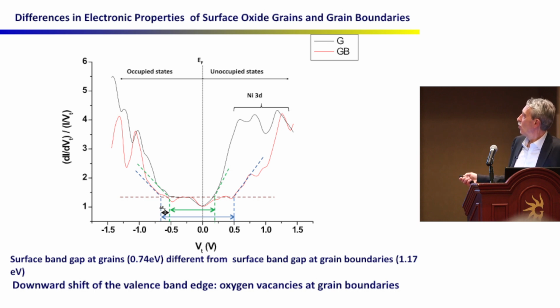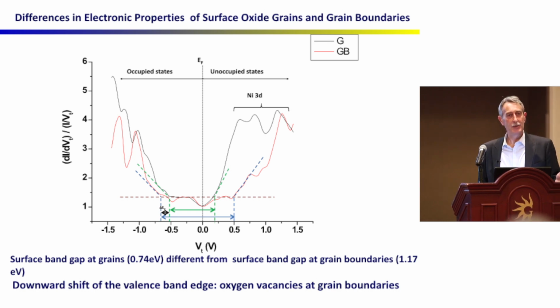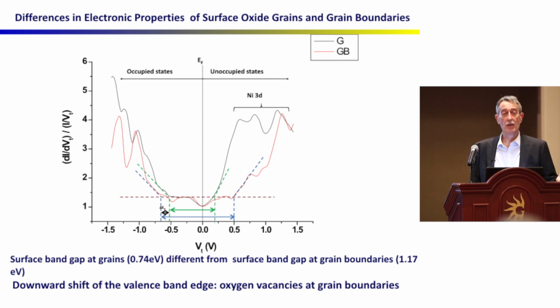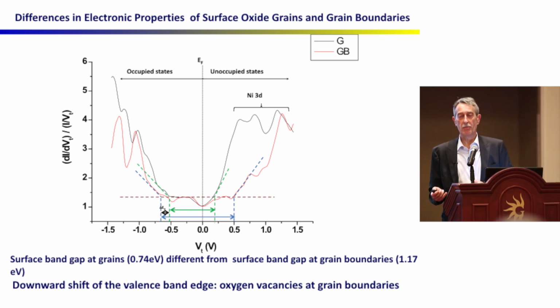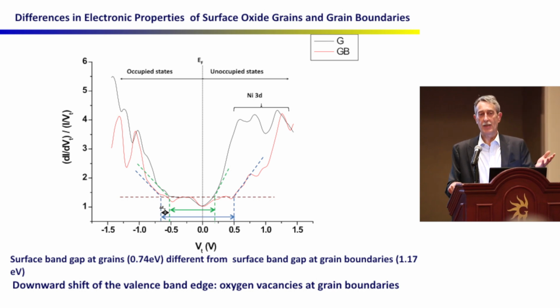It goes to lower values on grain boundaries, and this downward shift of the valence band edge is indicative of the presence of oxygen vacancies. That proves that we have more oxygen vacancies at the grain boundaries than in the grains. And of course, oxygen vacancies mean a locally more reactive surface towards anions like chlorides. So from that, you could expect that these locations will be preferential sites for pitting.